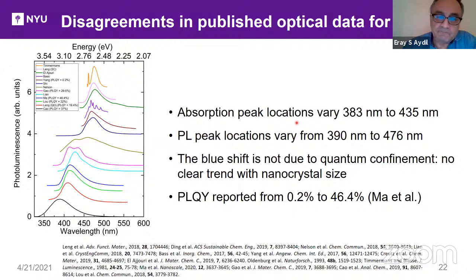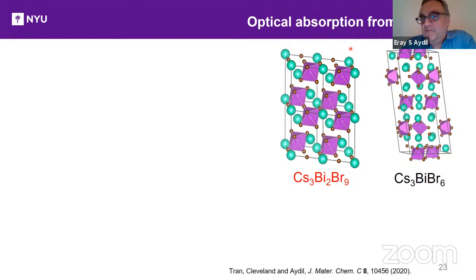So what does optical absorption from the physical vapor deposited films look like? Here is the Cs3Bi2Br9, this is the trigonal, and here's the other, monoclinic structure. I wanna point out a couple of things here. One is that if you look at the octahedra here, even though it's not obvious from all of them, they're all corner to corner connected. So there are no isolated octahedra here. Whereas in the monoclinic material, the octahedra are isolated. They're almost like quantum dots, if you will, of octahedra. And I should also point out that this looks a lot like BiBr6 ions floating in a liquid.